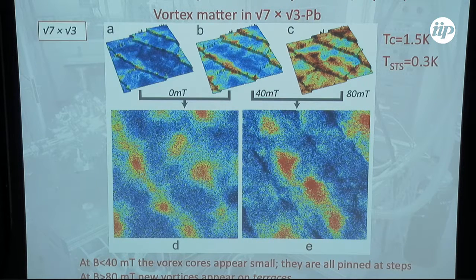these steps are intrinsic Josephson junctions, because the thickness of this superconductor is just one atomic layer, and this is a disruption. So you have a Josephson junction, and then if you apply a magnetic field and you do some mathematical subtraction of your map at, for instance, here at 40 millitesla minus the map at 0 field, you immediately see that there are vortices all sitting on steps. And these vortices, I will just explain in a few minutes, are intermediate Abrikosov-Josephson vortices. They are not purely Josephson vortices. It is an intermediate case that Alex Gurevich predicted in '93. And once you have saturated your steps by these intermediate Abrikosov-Josephson vortices, other vortices appear inside terraces, as you see here, and more clearly here. Okay, their number is perfectly what is expected considering phi naught and the surface of this image.